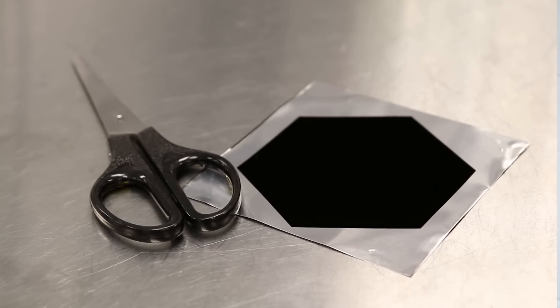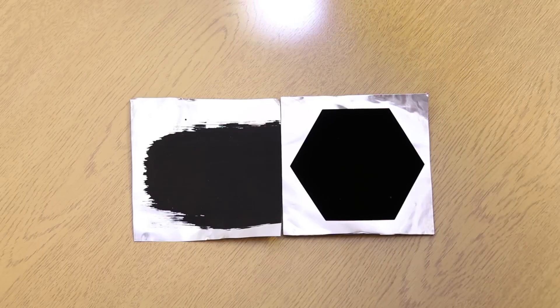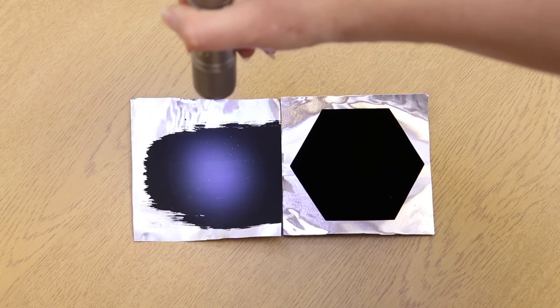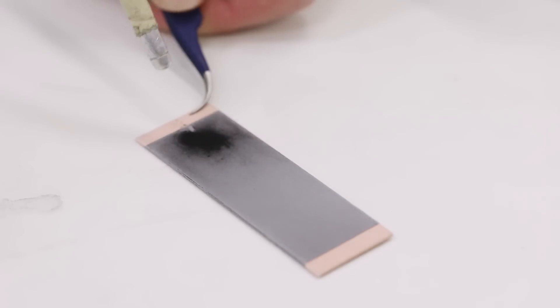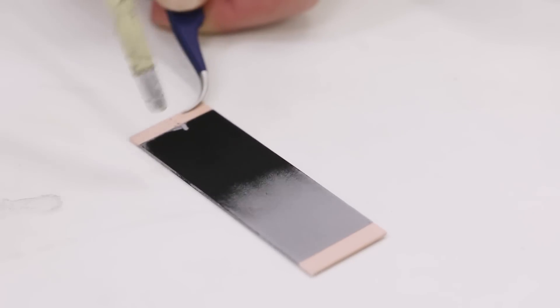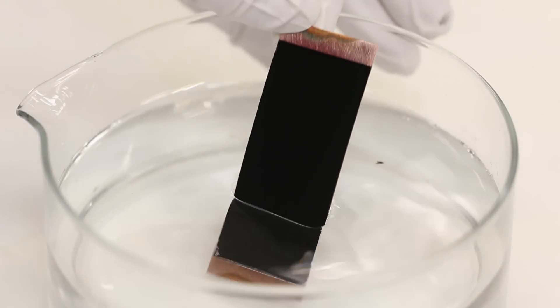So what you look at looks incredibly black, but the reality is if you try to touch it, there would be nothing there to feel, because it's almost all air. Typically a black paint is about 5% reflectance, whereas Vantablack is down to 99.965% absorption. To make a material that's 100% absorbing, it would have to have no solid form, because some light will always bounce off the top of it before it enters into the structure.